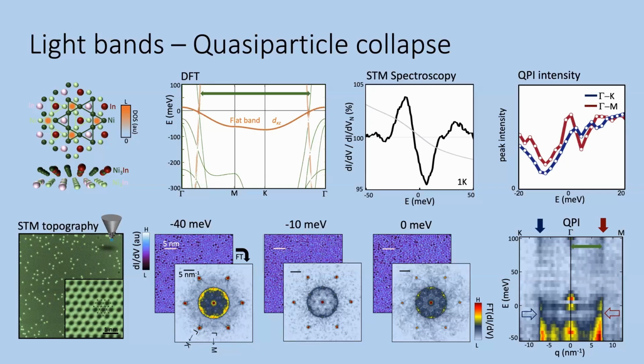Moreover, this data was taken at 4 Kelvin within the non-Fermi liquid phase. When we now cool the system and repeat the measurement at base temperature within the Fermi liquid phase, we see that this dip completely goes away, which is, of course, against any thermal broadening scenario that should result in the opposite. The more we warm the system, the more features wash out. Here we start with a well-defined dip at high temperature that disappears when we cool the system. So the system really seems to lose its coherence when we go to 4 Kelvin within that energy of the flat band. And maybe just a final comment.